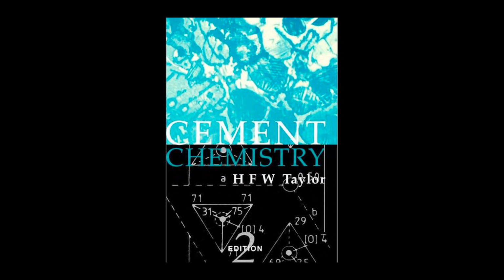Let's detail the chemical cascade of carbonation. It's not just CO2 hitting the surface, is it? No. Atmospheric carbon dioxide dissolves in the pore solution and forms carbonate ions. This CO2 is acidic, and it chemically attacks the cement hydrates. It consumes the crystalline calcium hydroxide, which is the primary source of alkalinity, and at the same time, it starts decalcifying the CSH gel itself, lowering its Ca/Si ratio. And the pH falls dramatically. Yes, as decalcification proceeds, the CSH is ultimately reduced to a less protective hydrous silica structure. The pH of the concrete cover drops below 8.5, which is the critical threshold. Once that happens, the steel's passivation layer breaks down, allowing corrosion to begin rapidly in the presence of oxygen and moisture.